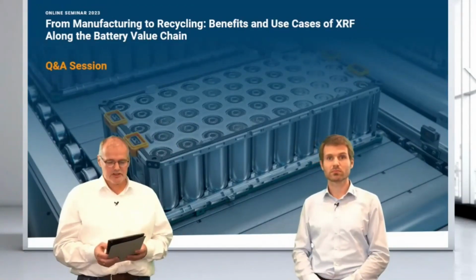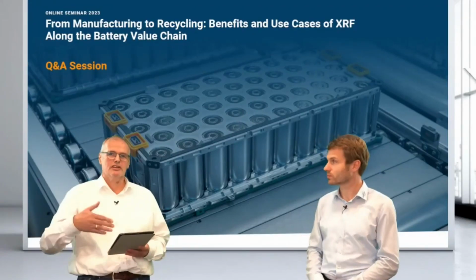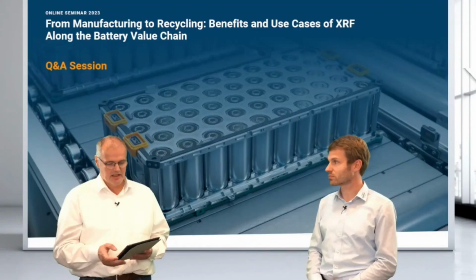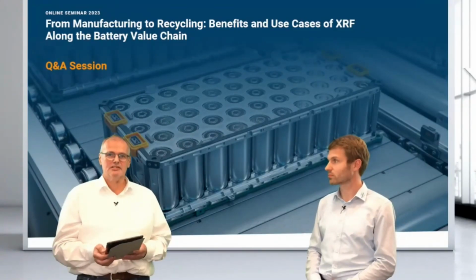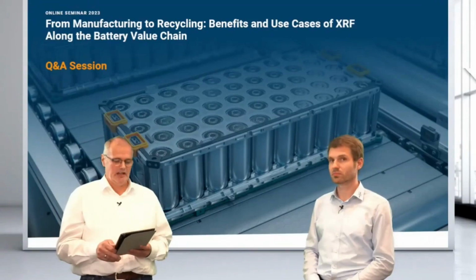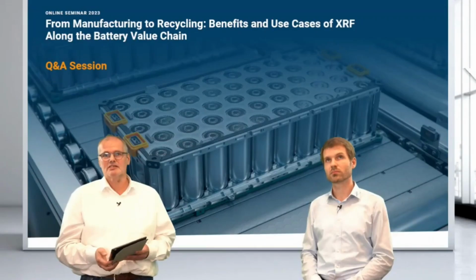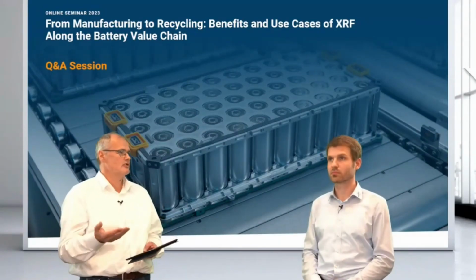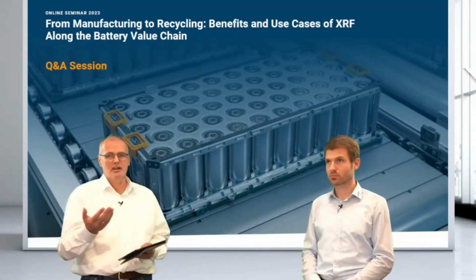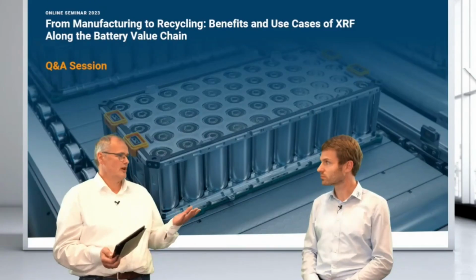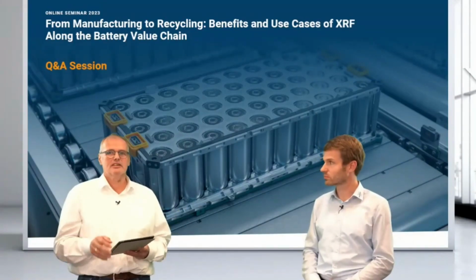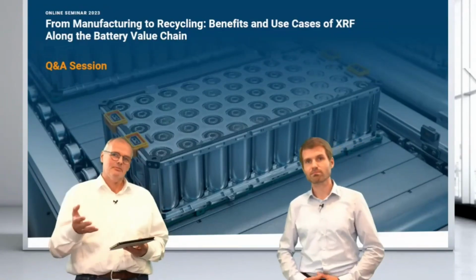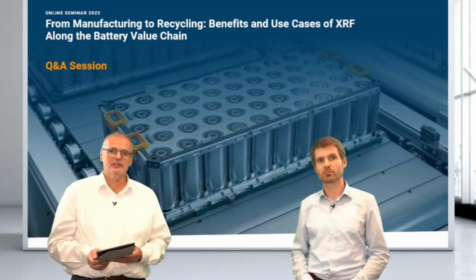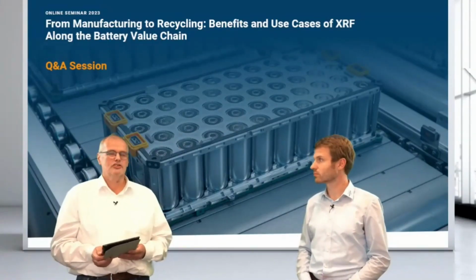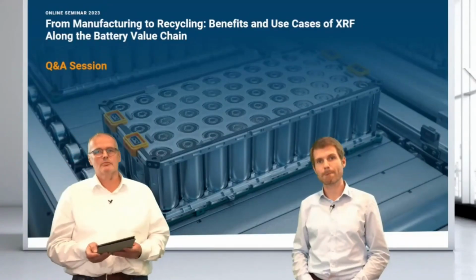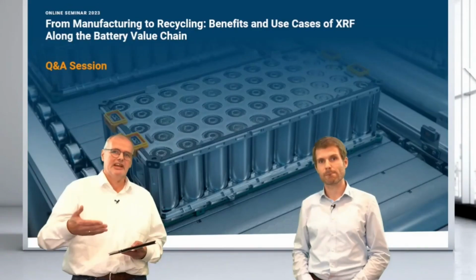One of the questions relating to this, when looking at the cells and especially at recycled materials, is how do we handle matrix effects, like looking for the heavy or transition metals like manganese and nickel, and then considering there are amounts of carbon and aluminium inside after you're shredding, for example. The interesting thing in XRF is that those inter-element effects are basically theoretical factors which are known from physical determinations. So they are in a library. This is the one thing. So matrix effects are taken into account.